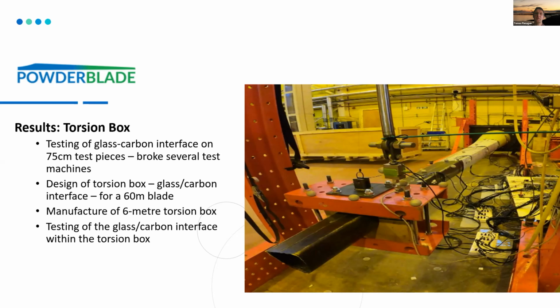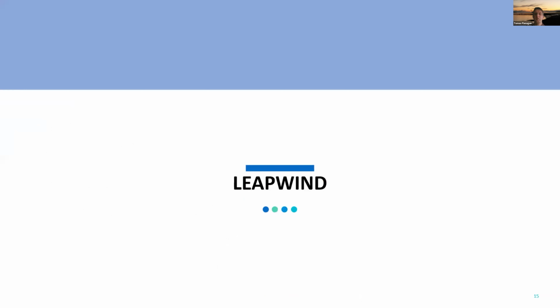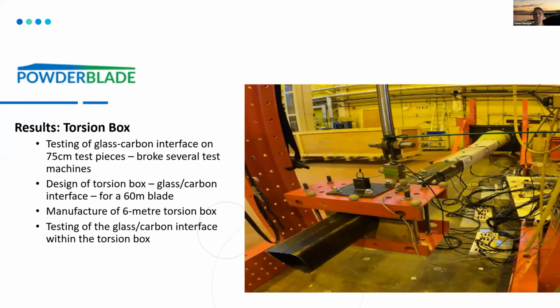And it was a pretty detailed test. A lot of data was captured, and the behavior at the glass-carbon interface is something that doesn't get an awful lot of discussion in the literature, but that is a pretty big problem for industry, where they're trying to make blades that have carbon for the load-bearing elements, but glass for the root section where it's thicker by definition. Also, the stiffness is another advantage of the carbon, because it reduces the pre-bends that you need for the really big blades, going sort of 60 meters plus. So that was a quick tour of the powder blade project and the powder epoxy project.